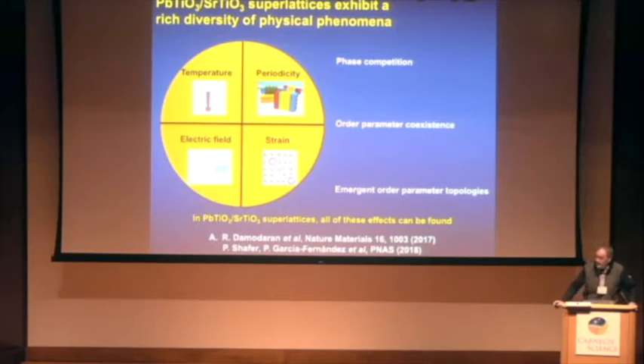So if we look at the bulk level, at the lead titanate, there are two phases that compete. One of them is the ferroelectric distortion at gamma, and the other is the antiferrodistortive distortion. So at the bulk level, the ferroelectric distortion wins and inhibits the appearance of the second. Regarding strontium titanate, it's a quantum paraelectric and undergoes an antiferrodistortive phase transition at 105 Kelvin.